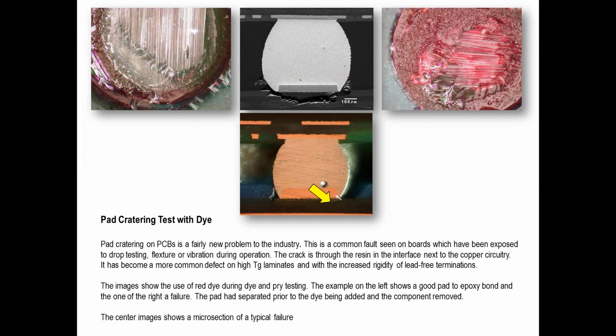Now, pad cratering is a defect that hopefully not too many people have experienced, but literally it's the pad separating from the PCB. And it's all to do with the mechanical force applied to a joint, a component, or the board during the assembly operation or after the assembly operation. A lot of the high temperature laminates don't have the same adhesion of the copper pad to the substrate, and also the epoxy resin used within some of these materials is much harder. So any of the energy literally goes into that interface rather than being absorbed by the solder joint.